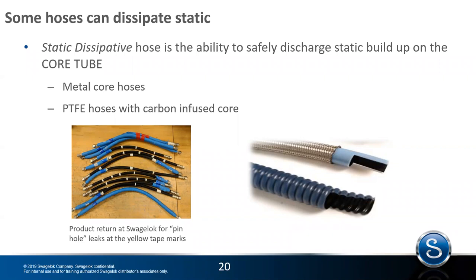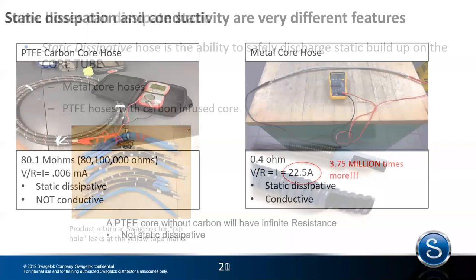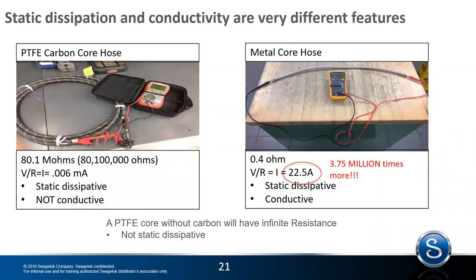And that's what you see on the right, a black carbon core. The Teflon becomes black because of the carbon, and it allows for a small amount of electric flow so that the electrons don't jump through to the braid. They actually flow through to the braid or flow through the end connection, whatever the nearest ground is. These two examples, and it's a bit technical, I understand, show the difference between a conductive hose, which is what you see on the right. This hose has a metal core, a metal braid, and metal end connections. The entire hose is conductive. It will flow a very high amount of electrons.